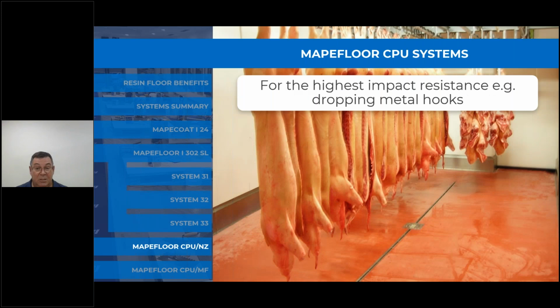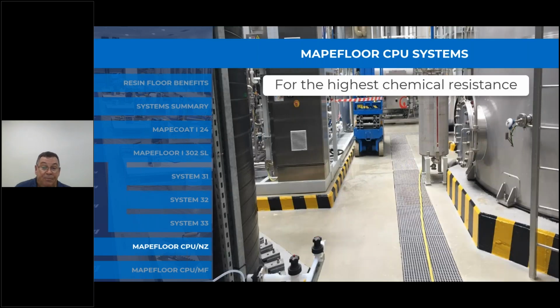For the highest impact resistance, the dropping of metal meat hooks and the like in an abattoir or any preparation areas, the cement polyurethane system offers extremely good impact resistance compared to the more brittle epoxy, which can tend to shatter when enough force is exerted on point load. So also for the highest chemical resistance, the cement polyurethane systems also offer extremely good chemical resistance. So where there's abrasion requirements, where chemical resistance is a requirement, and where you have impact and maybe thermal shock, the cement polyurethane system is by far the best choice.